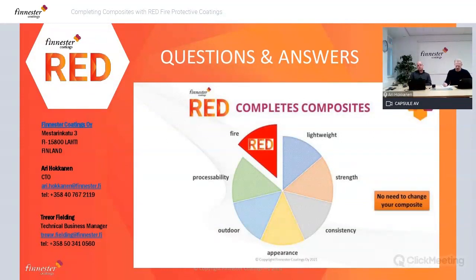Okay, here's a nice one for you, Ari. Do you know how the intumescent char behaves under vibrations? Can the char layer paint detach away from the composite substrate when fired under vibrations? That's a very good question, and this is why we have designed this 2-layer system. If you have only an intumescent layer, the char is more or less fluffy and light. So when you have vibration, it will fall on the floor. With this system, we have two separate layers. You have that ceramifying bubble that protects the intumescent foam underneath. So it's fully reliable under stresses and vibrations and airflows.